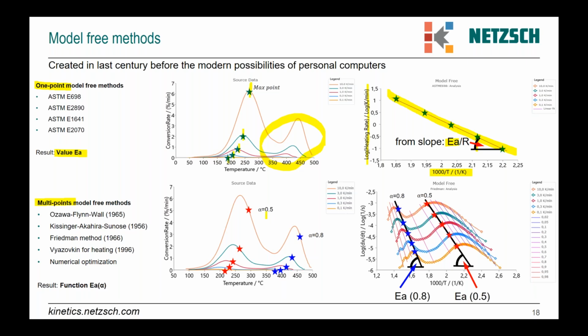Here, not only one point, but several points are taken into account. For example, the point with one value of activation energy, here is 50%. Then we have some points from different curves. On the Arrhenius plot, it is one line with a slope, and from the slope activation energy for this conversion could be found. Then the same could be done for another value of conversion, for example, for 80% conversion. Then there is another line, another slope, and another value of activation energy.